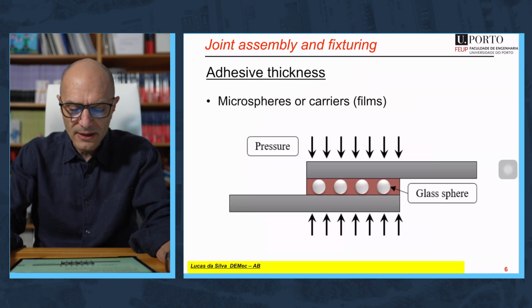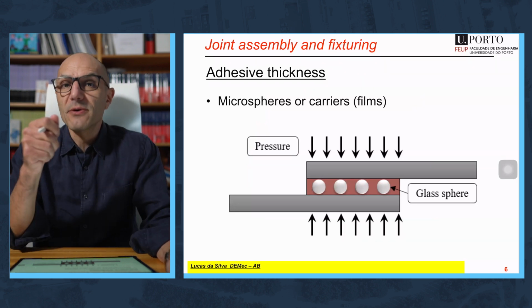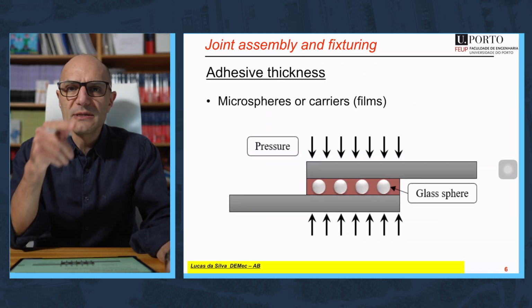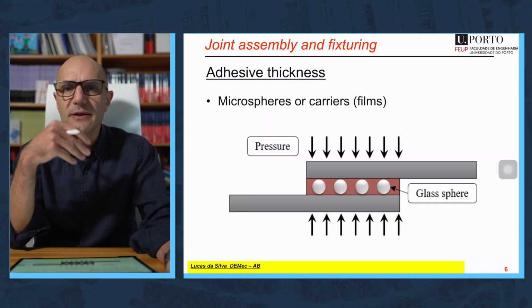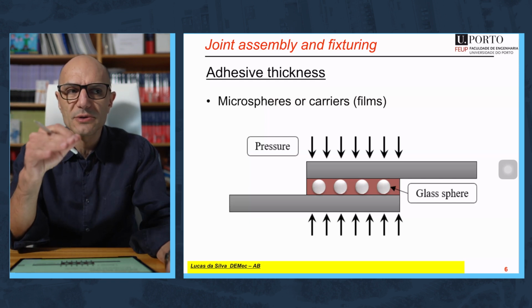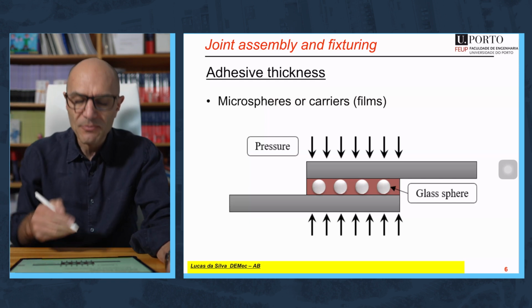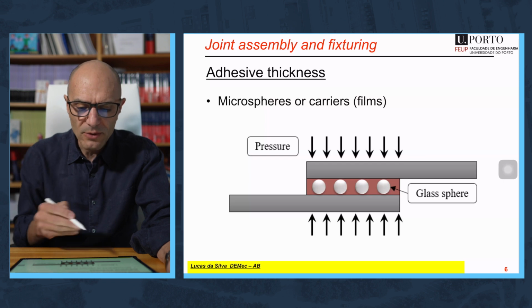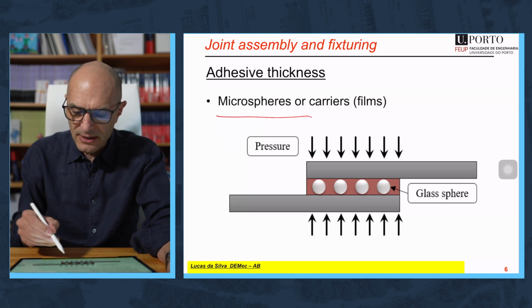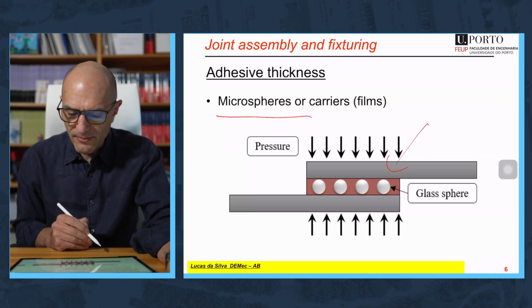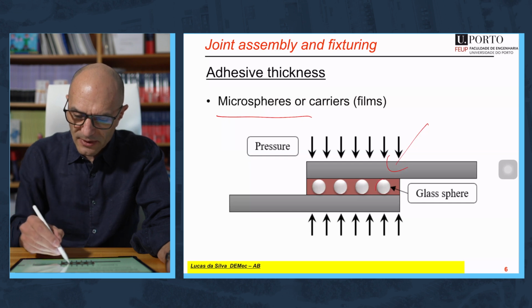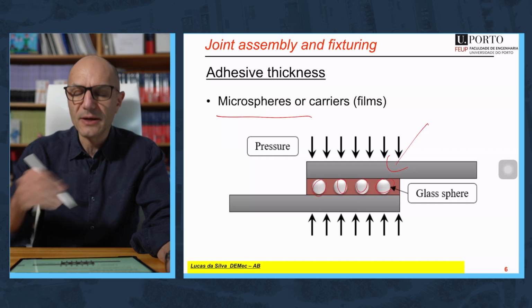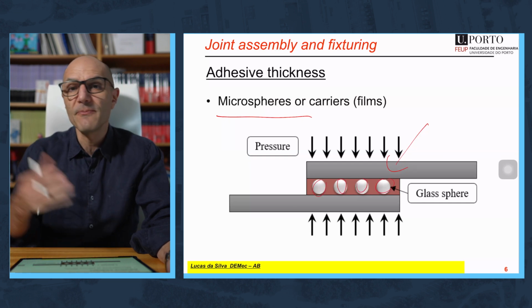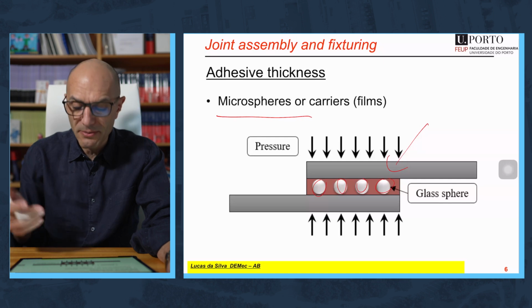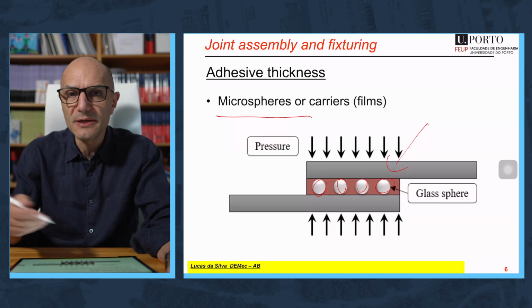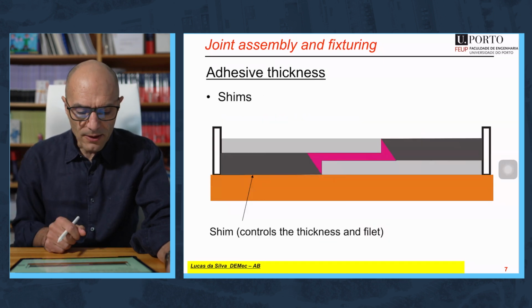About the adhesive thickness, that's a very important parameter to control because this will have a big impact in the final joint strength, so we should control this very, very precisely. There are several ways to do it. One way is to use microspheres, such as the scheme indicated here. These are the microspheres. We can mix this into the adhesive. Some adhesives, it's already pre-mixed. We call it also ballottini, these glass spheres.